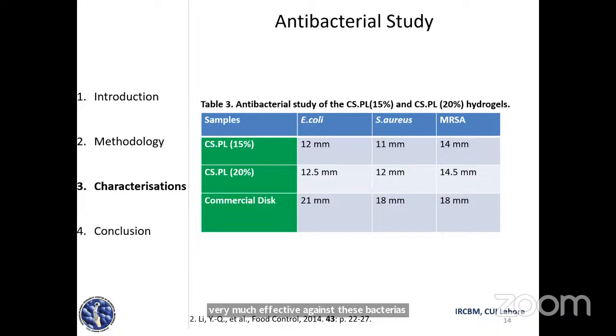And this zone is because of both PL and CS, chitosan. It has amino groups, and these positively charged amino groups bind with the negatively charged bacterial surface. They hinder the growth, decrease the synthesis of DNA, and cause cell death. And the same mechanism is shown by poly-L-lysine.